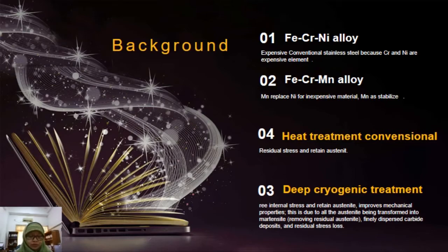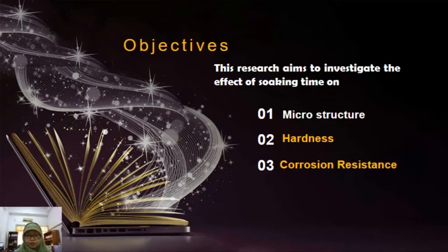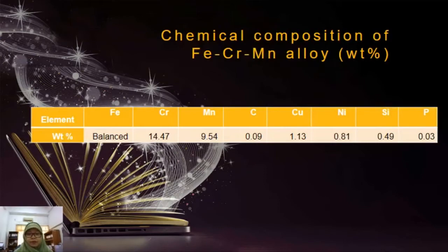Various studies have proven the effect of deep cryogenic treatment on various alloys, but the deep cryogenic treatment of Fe14Cr9.5Mn alloy has not been specifically studied. This research aims to investigate the effect of soaking time on hardness, microstructure, and corrosion resistance. The chemical composition of FeCrMn alloy is Cr 14.47, Mn 9.54, C 0.09, Cu 1.13, Ni 0.81, Si 0.49, and P 0.03.